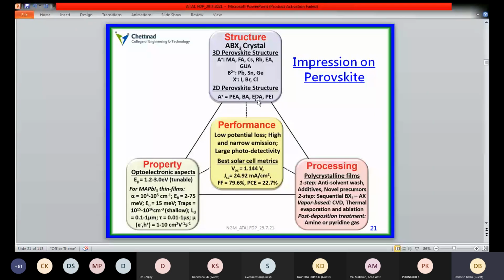After that, they analyze the properties, especially the optoelectronic aspects, to find the optical band gap value. If it falls in the range of 1.2 to 3 electron volts, then only it can be useful for PV applications. It is found that when we change the A site, B site, and halide atoms, the band gap energy can also be tuned. So the tunable band gap is an important property of perovskites. And the most important one is the processing of the perovskite films.